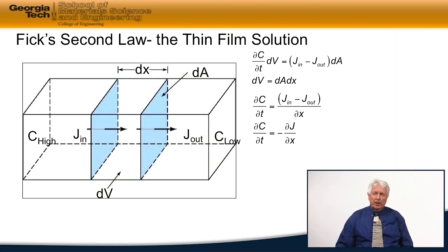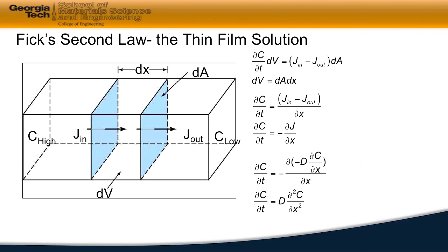Now, we know that we can write an expression for the actual flux in terms of the expression for Fick's first law. So now what we can do is substitute, and now we have an equation that relates the change in composition with respect to time on the left-hand side of the equation and the diffusivity on the right-hand side along with the second derivative of the change in composition with respect to position.